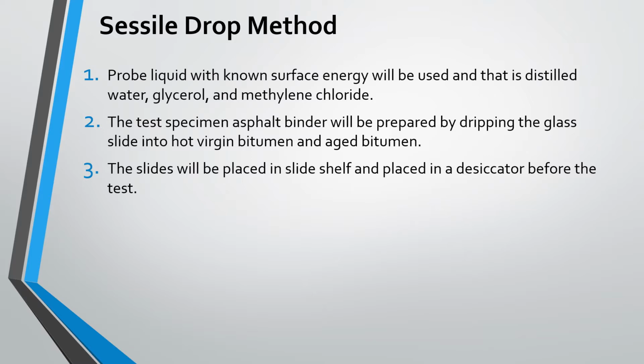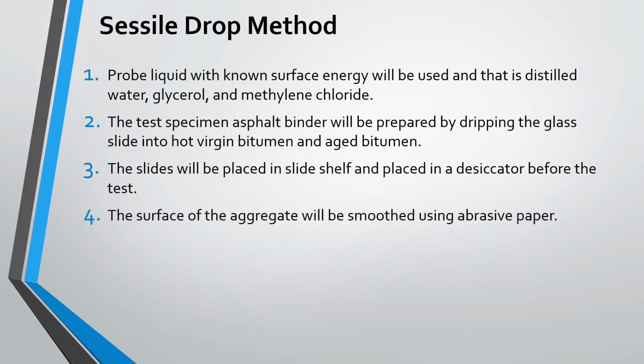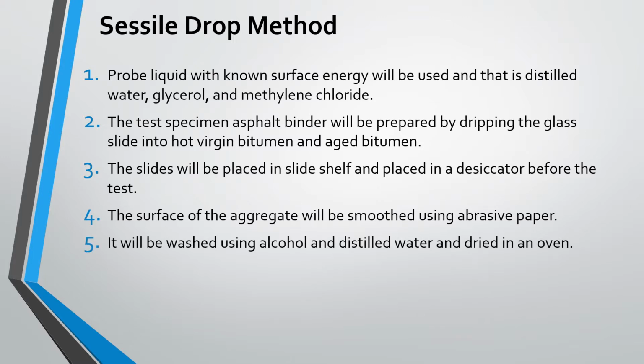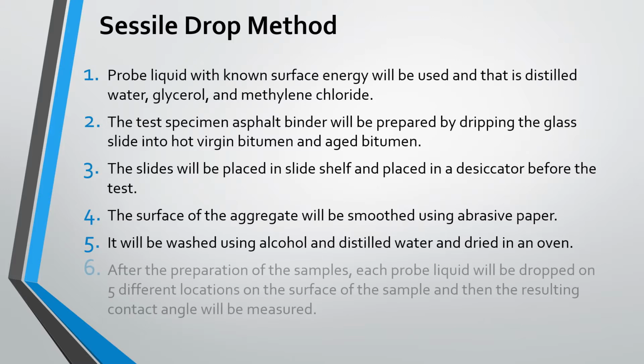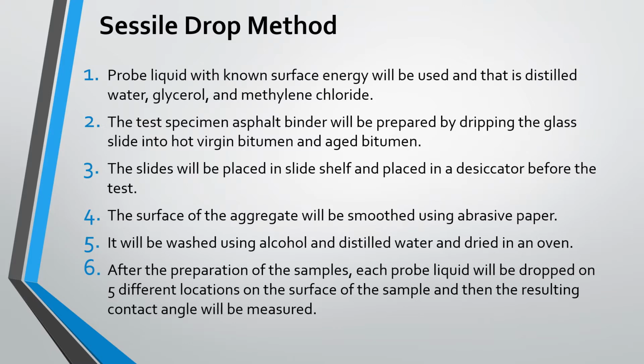The surface of the aggregate will be smoothed using an abrasive paper. It will be washed using alcohol and distilled water and dried in an oven. After the preparation of the samples, each probe liquid will be dropped on 5 different locations on the surface of the sample, and then the resulting contact angle will be measured.